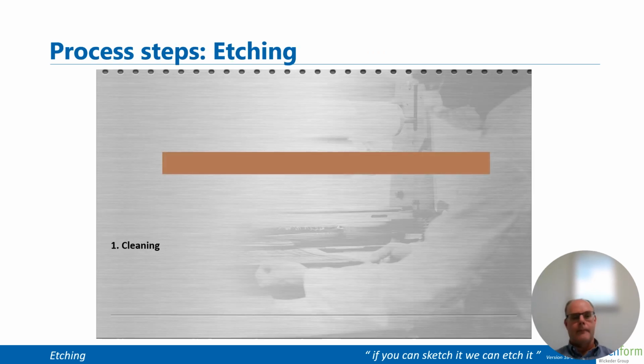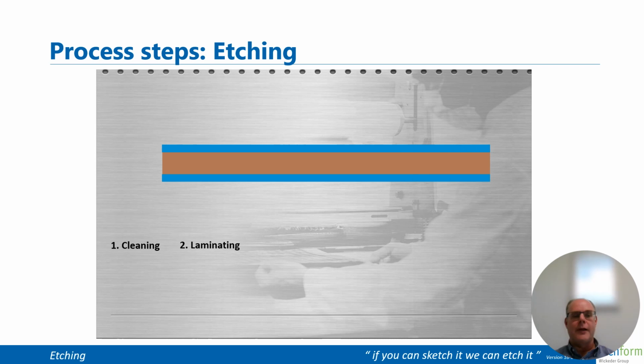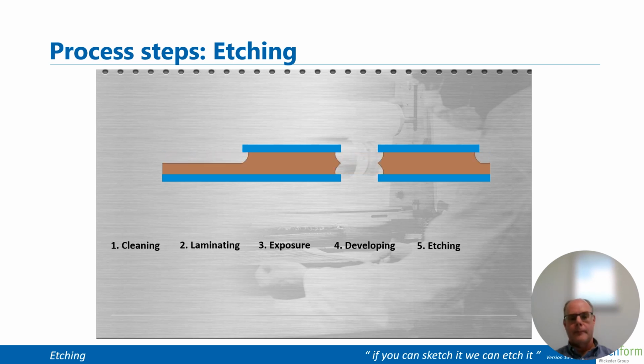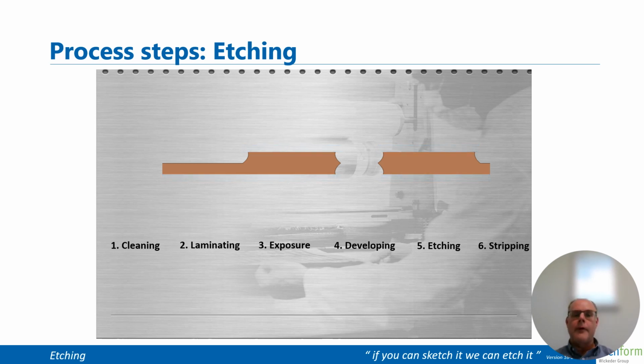How does the process look like? Well, we start with the base material cleaning to remove any rolling oils or fingerprints and so on, to get a good adhesion of the photoresist that's laminated on it. Then we expose this photoresist: where it sees the light, the resist is polymerized, and where it doesn't see the light, it stays soft and can be developed away in the next step. Part of the metal is then unprotected, and this metal can be dissolved in the etching solution. And then the last step, we only have to strip the photoresist. The product is ready for final inspection.